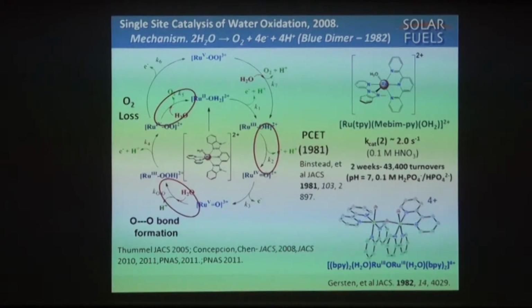Anyway, go back to the overall water oxidation cycle. The first thing to notice is it's complicated, and people complain it's complicated. But look at the net reaction. You have to take 2 water molecules and take away 4 electrons and 4 protons. There's no choice. In order to complete the reaction, you have to have complexity at an oxide surface or with any molecule in photosynthesis. The first step with this as a catalyst is oxidation to ruthenium-3. You can monitor that electrochemically or by chemical mixing experiments using strong oxidizing agents. It then goes on in the second step, having lost 2 electrons, to ruthenium-4.